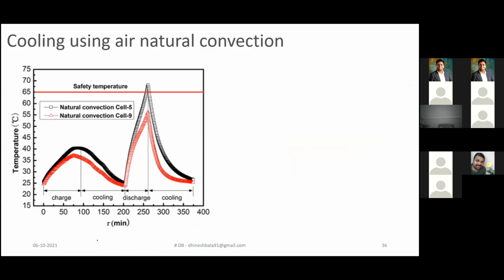What we are trying to do is make a plot between time versus temperature. Initially the room temperature is 24 degrees Celsius, and you are asked to charge your battery from 20% SOC to 100% SOC for a duration of 0 to 100 minutes. For 0 to 100 minutes, when you make a plot between time versus temperature, the temperature is raised from 24 degrees Celsius to 42 degrees Celsius.